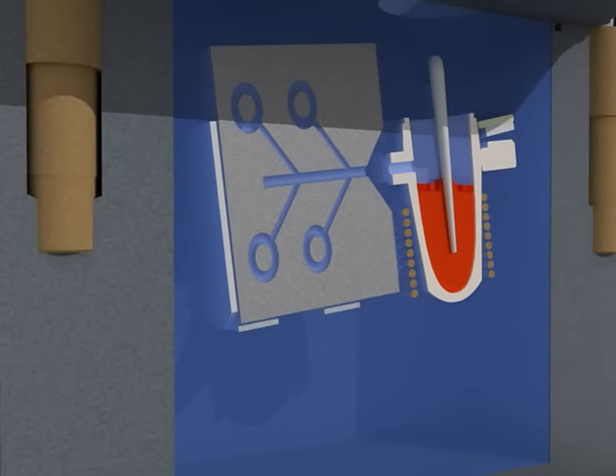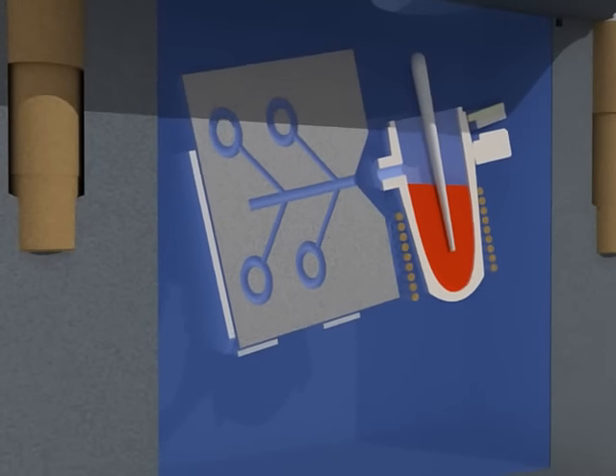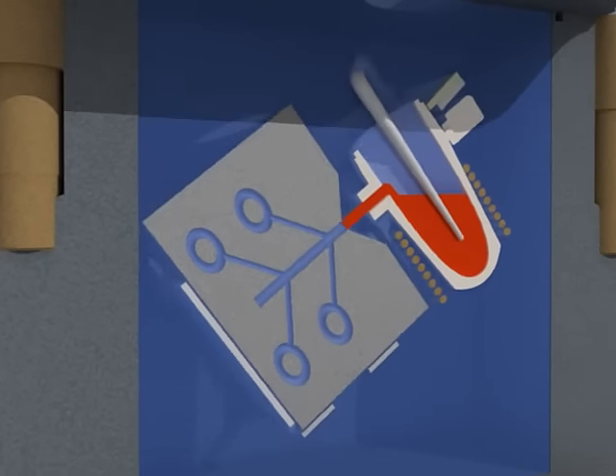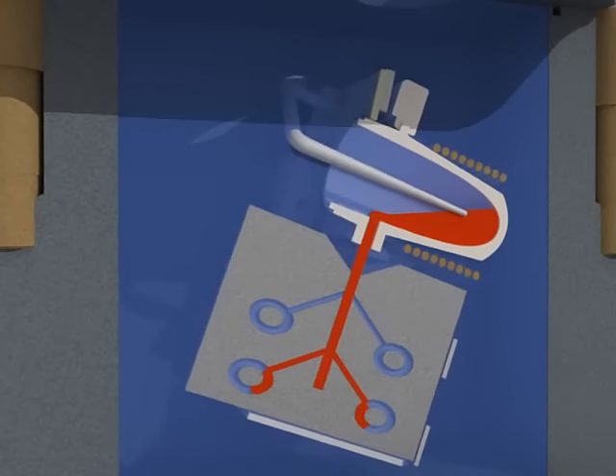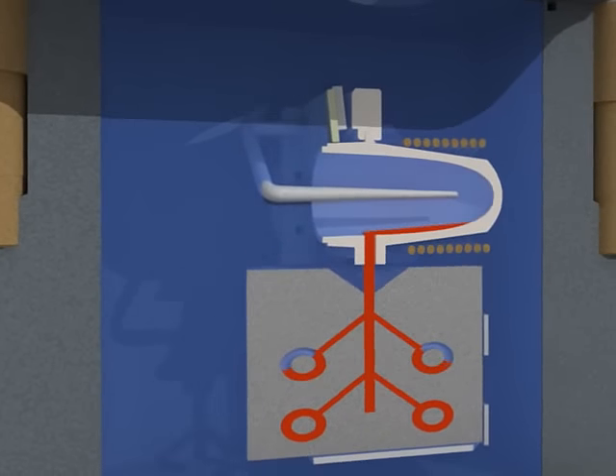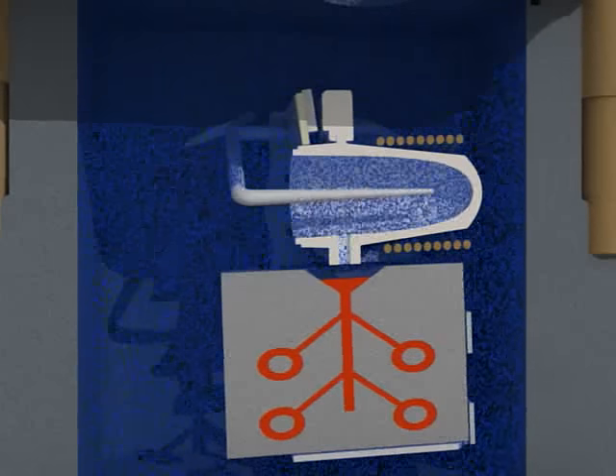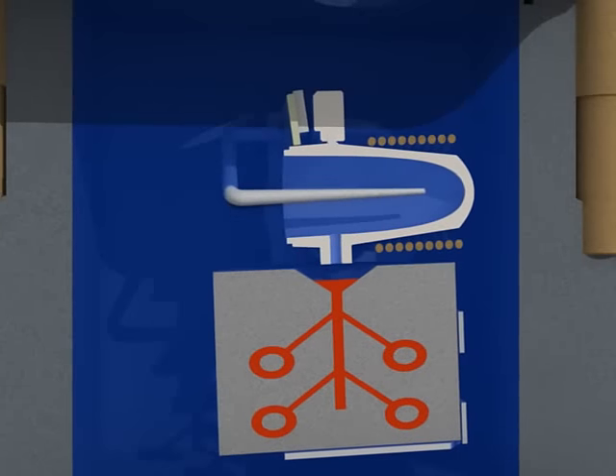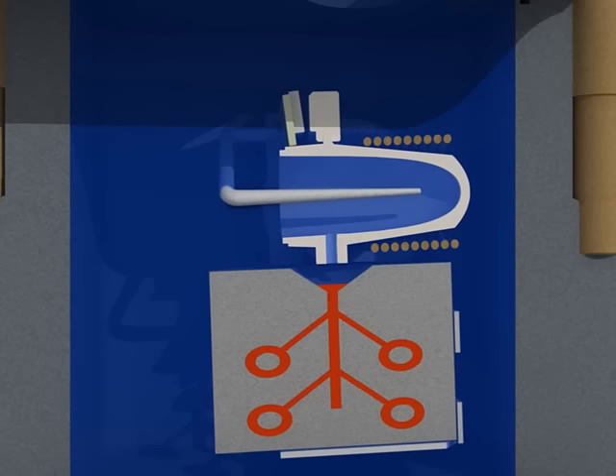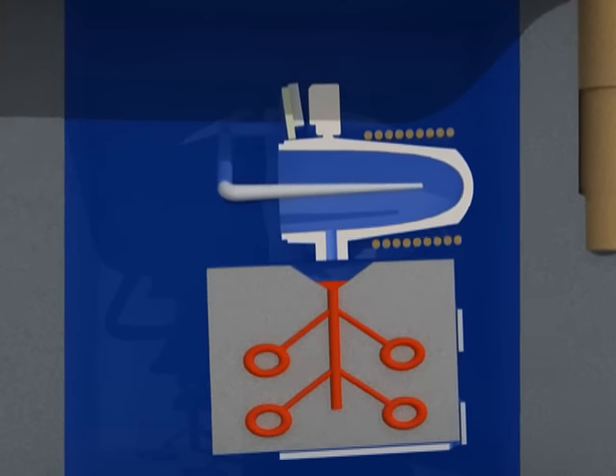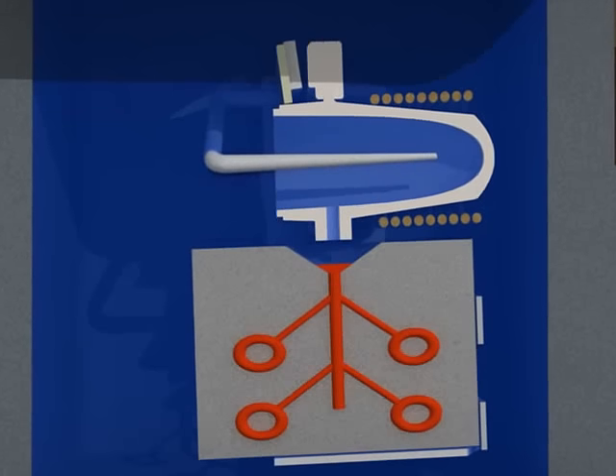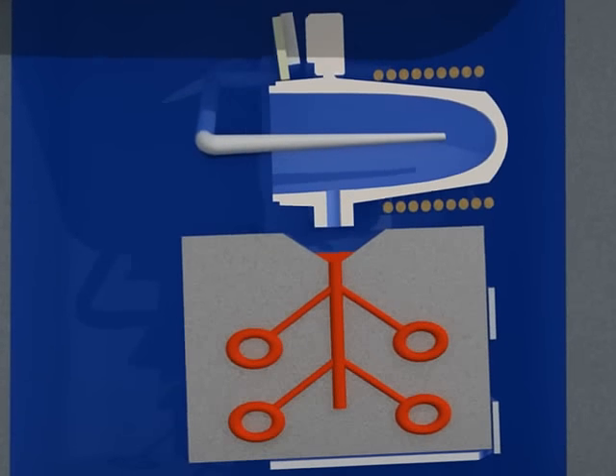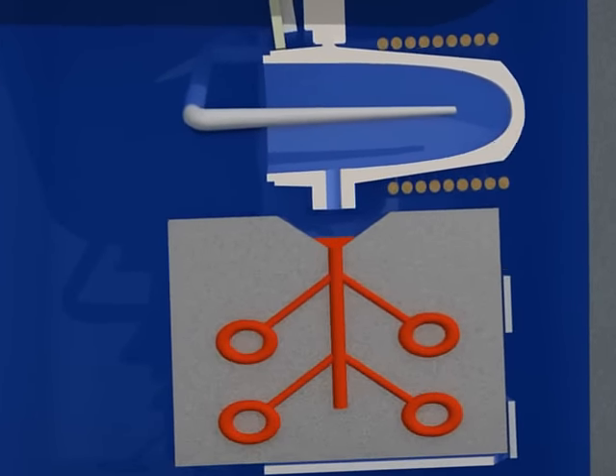At this stage, just by pushing a button, the whole crucible and flask system will automatically rotate through 90 degrees, and the metal, once poured in a homogeneous and controlled way into the flask, is automatically pressurized to 4 bars by argon gas. This high and quick pressurization is indispensable to obtain a proper and homogeneous filling, even at low